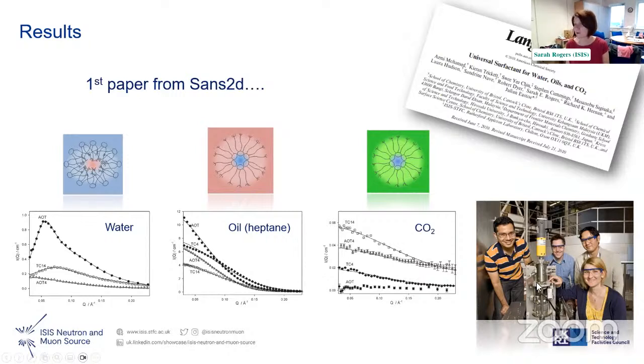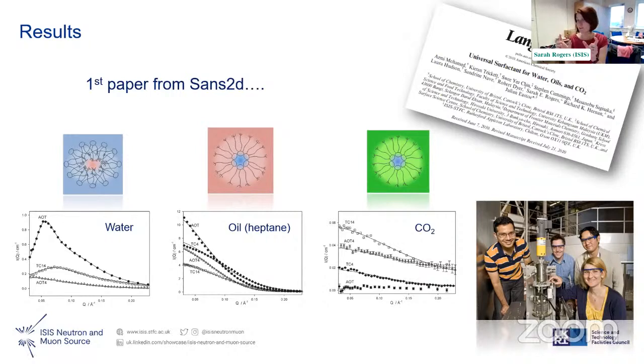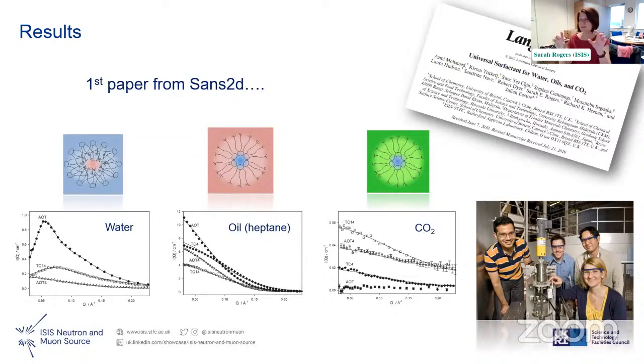The special pressure cell is solid steel, but the windows are C-axis cut sapphire — very chunky to withstand up to a couple of kilobar, but totally transparent to neutrons. This shows you can design really complex sample environments, and if you choose the right window material, the sample environment becomes invisible to neutrons and you only scatter from the sample of interest.